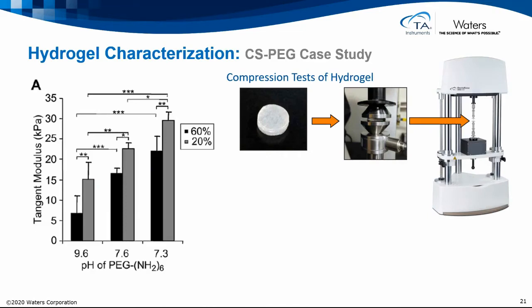So here's one of their first plots with the resulting tangent modulus and a couple different variables. The x-axis is varying the pH of the precursor solution, and then secondly, in the different bars, 20% or 60% is the relative humidity during the processing. So let's talk about tangent modulus for a bit. Essentially you can think of this as stiffness or hardness of the material, but specifically the modulus is the slope of the line between stress and strain.